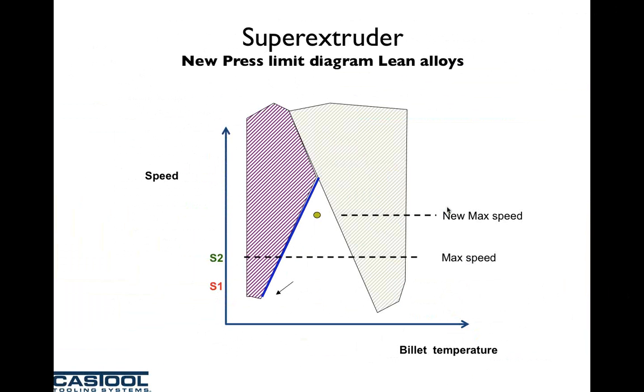So what's interesting is if you look at the press limit diagram for super extruders, they have a different set of diagrams. By using lean alloy with a high performance die, they are able to bump up the maximum speed to a newer maximum speed. So if you look at this diagram, right now it is steeper, so the peak is higher. They do have additional productivity gain out of it. And again, this is all through temperature control.